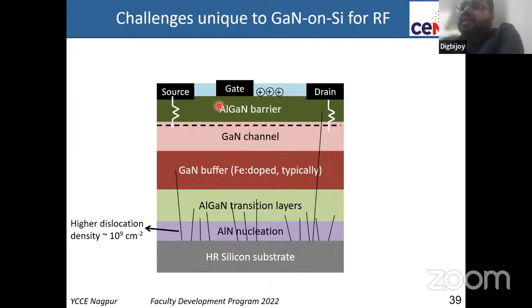Whenever there's an RF signal, there can be capacitive coupling to the substrate. So you might lose some RF power, radio frequency power. And so these defects and dislocations, the way we grow these layers, how much RF loss is happening, all these need to be characterized very well. We need to understand this very well so that we can make a platform which gives you really low loss on RF. Okay. So that's very important.